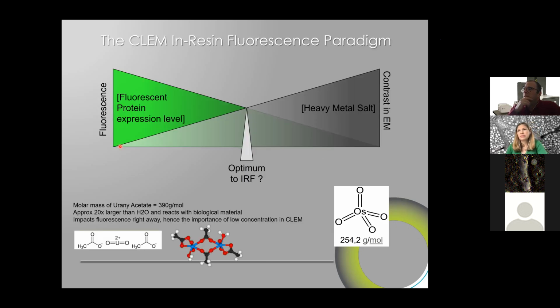And so the problem is that when we do this freeze substitution, we come up with fixatives and with some stain. And these guys, they come and they just fix the proteins together, and somehow they prevent the molecules from resonating. And that's one of the key points: the GFP has to be able to vibrate to be able to fluoresce. And so if you put too much fixative, or if you put a resin that tends to attach to the groups, like amine groups in the epoxy resin, of the molecules, then you will start to prevent this vibration. And then the molecule, the GFP, will not vibrate anymore. And so there is some kind of an optimal situation where the addition of any fixatives or stain will start to decrease the fluorescence. But then this is what also gains you a significant contrast in TEM.